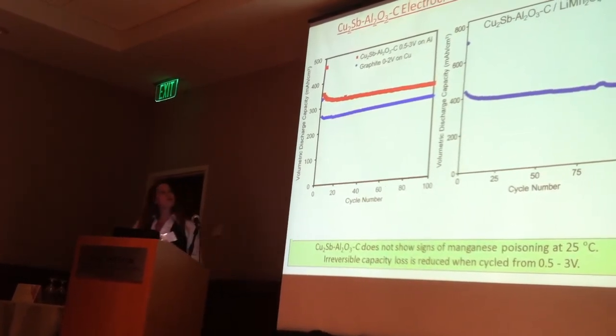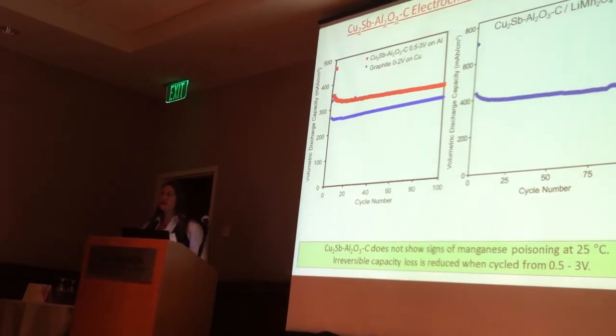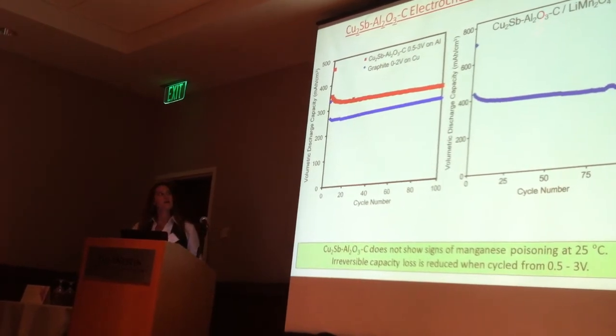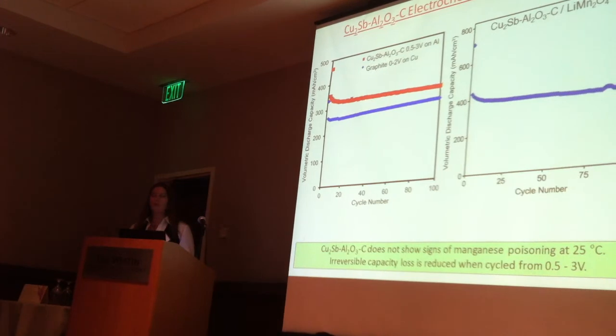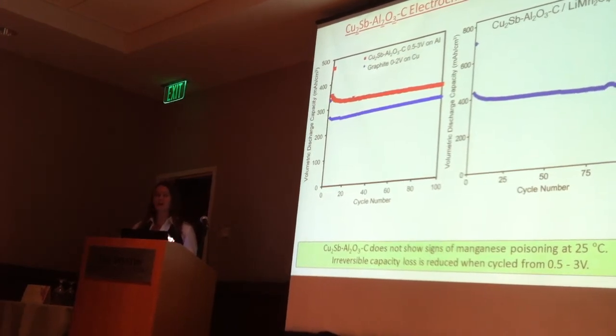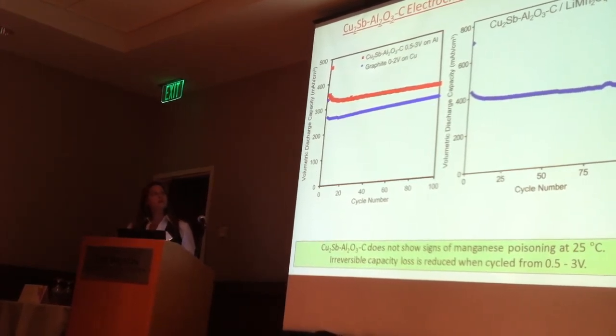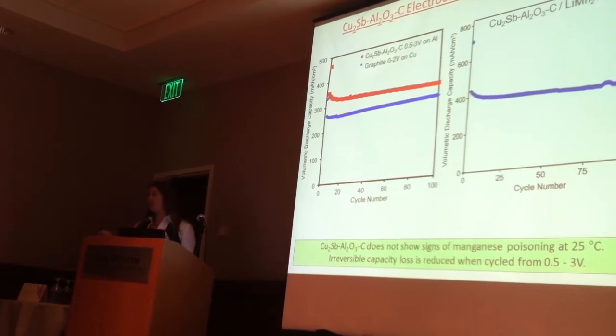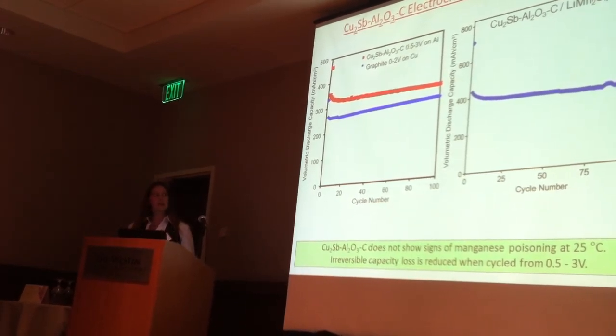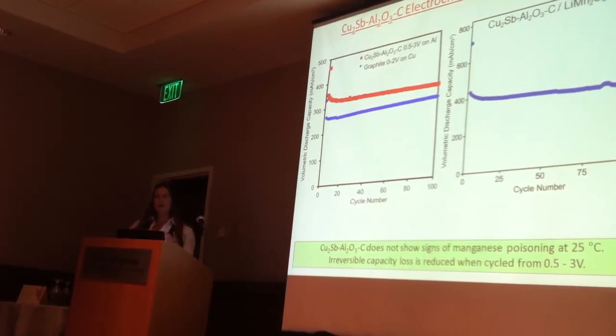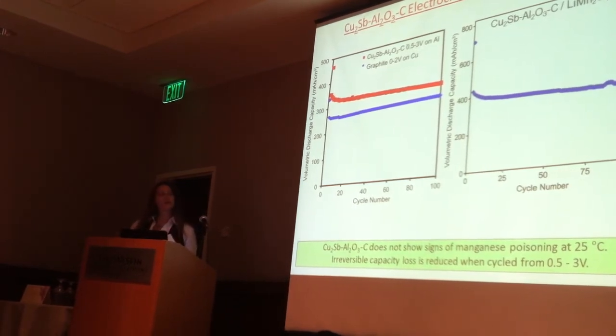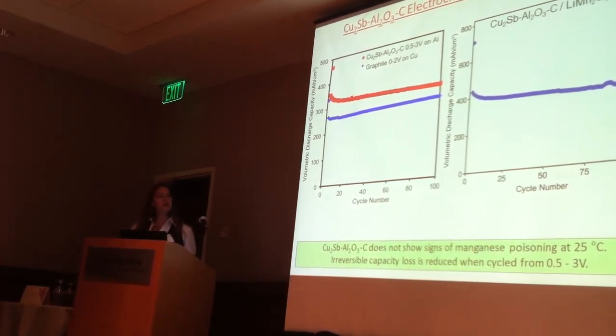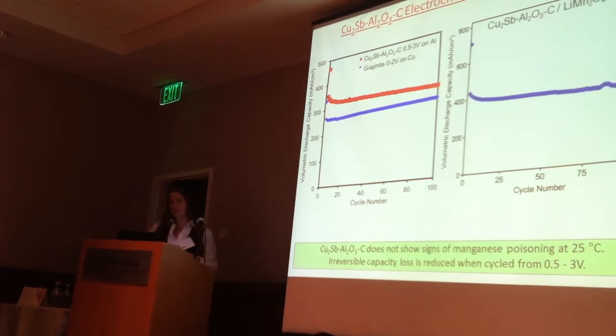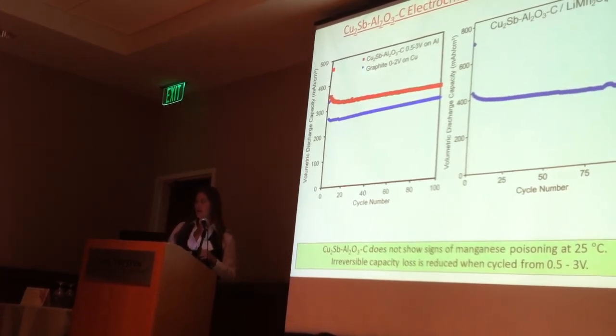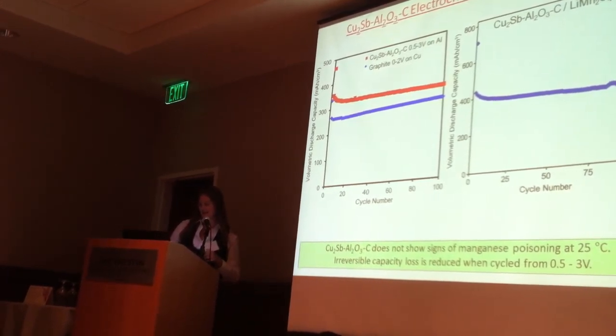We also have just started doing some full cell experiments, pairing our composite material up with manganese-containing spinel cathodes. This is a room temperature cycle test. We have some going now at high temperature, which will probably indicate more about our material's compatibility and resistance to manganese poisoning, but at least that's a starting point, indicating our materials might be compatible with those manganese spinel cathodes.